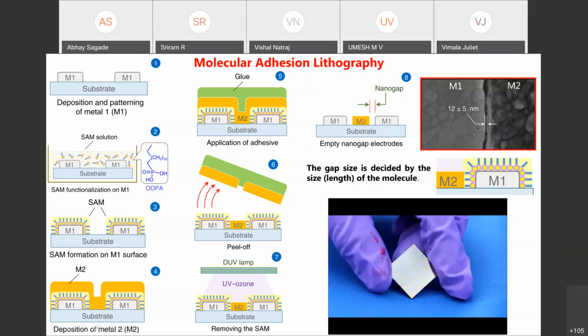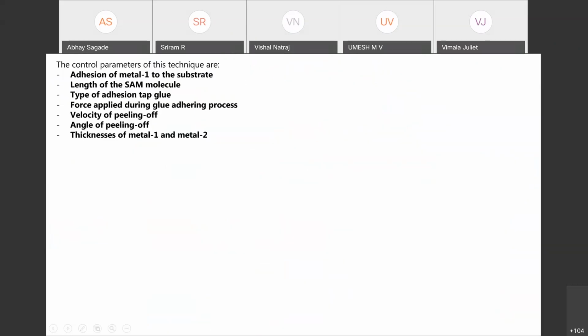So depending on the length of the molecule which you have used, you can end up with a gap between the two metals starting from 5 nanometers, and the maximum we could achieve is 25 nanometers. Gaps of 5 to 25 nanometers are very challenging to obtain from photolithography. Electron beam lithography is also one of the options, but access to it is not that easy. But with this combination of imprint lithography and photolithography, you can obtain small nano gap electrodes of the order of 10 nanometers. So there are various control parameters to obtain these nano gaps, which decide the yield.